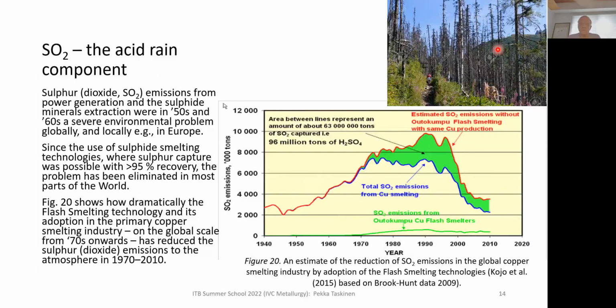That was one step further, and the other step was that copper industry gradually turned their processes into flash melting, where the SO2 capture is very good compared with reverbs or blast furnaces or roasters or electric furnaces using mixed calcine feed. And the trend is shown here.